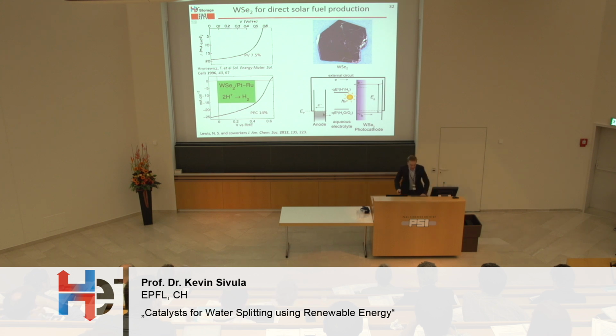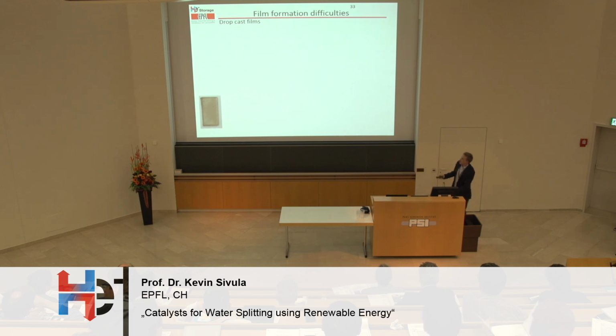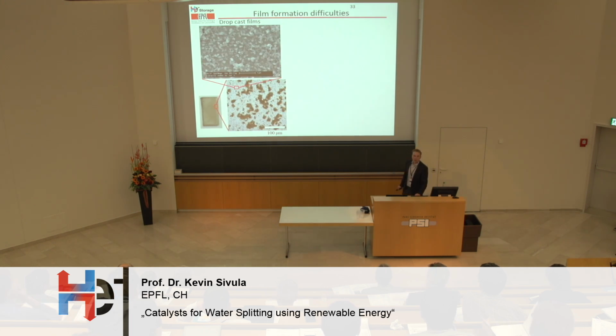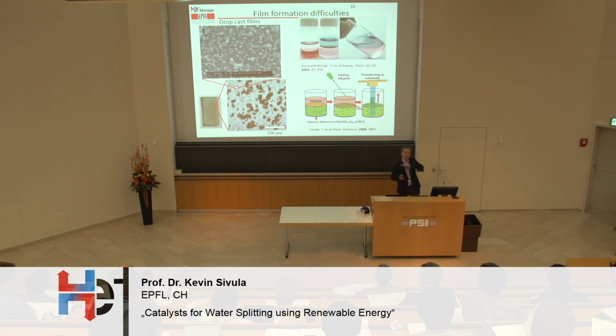I don't know. But our idea was to use our method to make very inexpensive electrodes of transition metal dichalcogenides with this material and see if we can get some solar activity for water reduction. Unfortunately, using the methods that we've developed so far, we have very poor film formation. It doesn't look good for semiconductor activity. So we took some inspiration from the literature, which uses simple types of self-assembly at 2D liquid-liquid interfaces, and developed a method to make very homogeneous thin films of our separated flakes. And on the next slide, I'm going to show you a video.